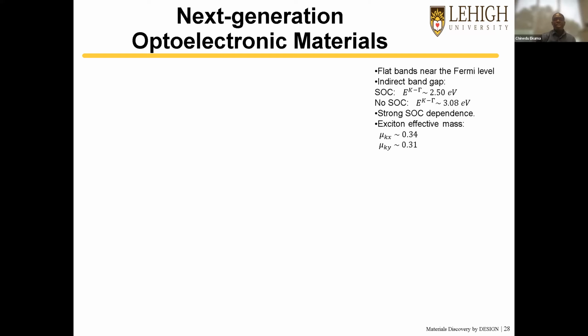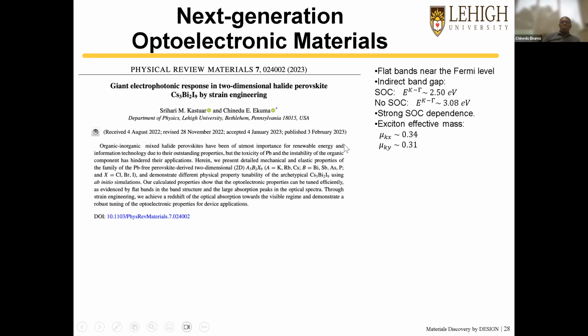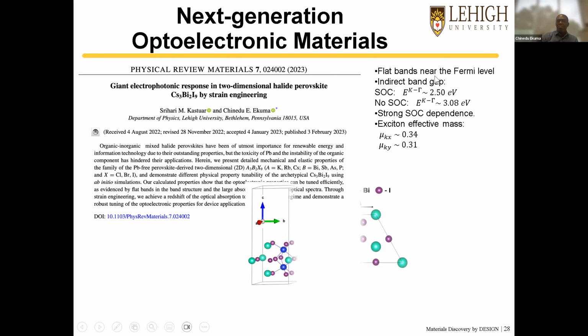So what I'm showing you here is another generation of new materials that we've been able to computationally synthesize in our group. And this is what we call all-inorganic derived 2D halide perovskites. So it's Cs3Bi2I9. As you can see here, these materials are characterized by flat bands. This is their structure. They have high, that is strong, spin-orbit coupling, and a relatively manageable exciton effective mass.